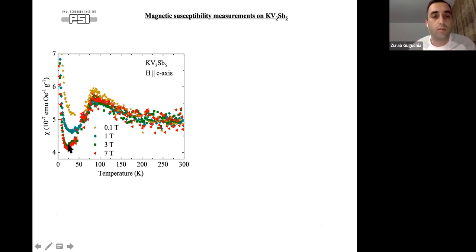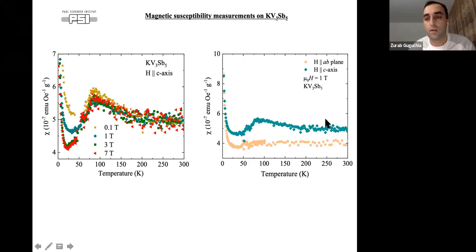So if we do the magnetic susceptibility measurements, you always see the charge density wave peak at the same temperature, but we see also here the increase of the susceptibility that somehow could be related to the same physics that we also see in the local magnetic susceptibility. But one important aspect here is that if you apply field in plane, there is no anomaly at the charge density wave. So you see it's strongest when you apply field along the z-axis. So the magnetic response across the charge density wave is clearly anisotropic.